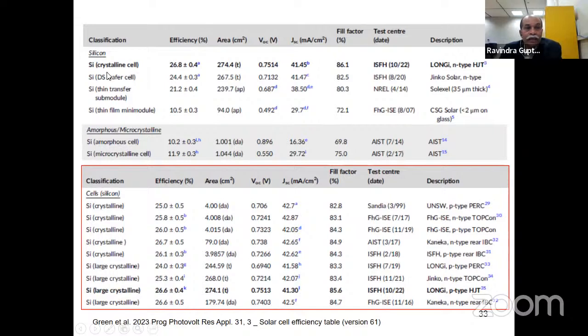So here you can see these are the standard. These are the reported and tested actually. So this is for the silicon-based solar cell. The area you can see is very, very high. This is from the company Longi, N-type HJT. This is 26.8%. But when we have directionally solidified wafer cell, it is 24.4%. But this area is also very, very good, you can see.